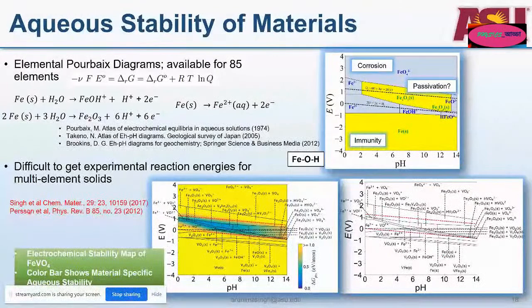What I did was develop an instability criterion, which is denoted by the energy with respect to the Pourbaix stable phase of a particular compound, with respect to its Pourbaix diagram. So what you're looking at here is the electrochemical stability map of a metastable compound, FeVO4. And metastable compounds by design cannot be on the Pourbaix diagrams. The Pourbaix diagrams only look at equilibrium compounds. What we did was generate this measure of delta G, that is the Gibbs free energy with respect to Pourbaix stable phases for compounds, and show them as a color bar.